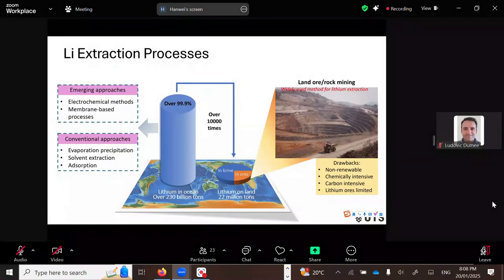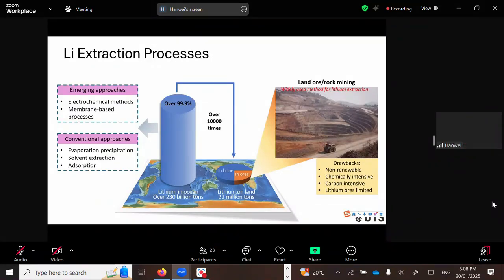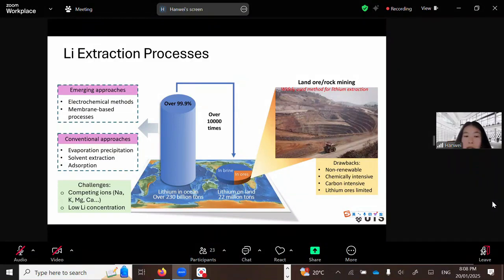So it's very challenging to extract lithium from seawater-based resources, because the lithium concentration in seawater and seawater brines is very low, and more importantly, there are a lot of competing ions such as sodium, potassium, magnesium, and calcium. The conventional approaches to extract lithium from aqueous resources include evaporation, precipitation, solvent extraction, and adsorption.